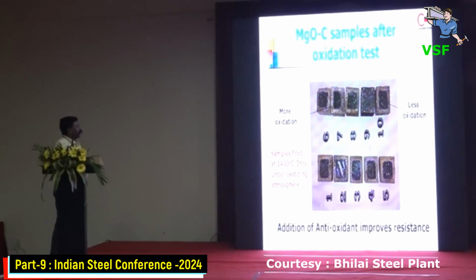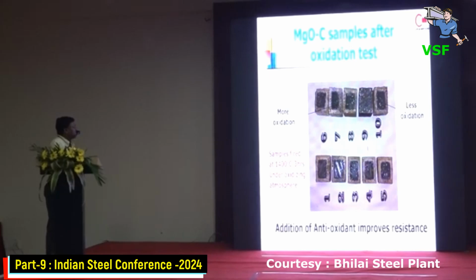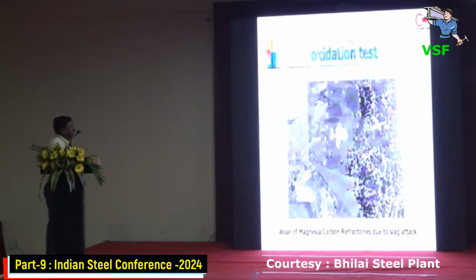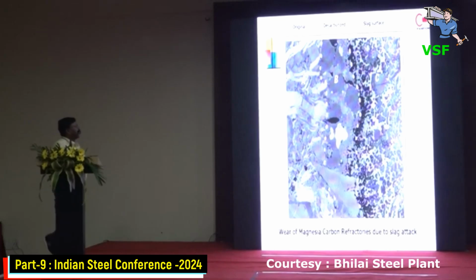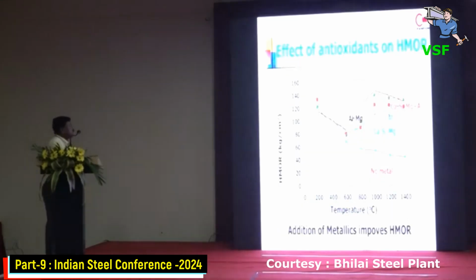This is one of the most important things, the oxidation resistance. We do the oxidation resistance test. The more white area is oxidized; the black is not oxidized. The more black, the better. For that we use some special antioxidant. If you collect a brick sample from the furnace, you can find different zones, like the slag surface, decarbonized and original. The more of that there is, the better. With this antioxidant, you can get the HMOR to more than 120.